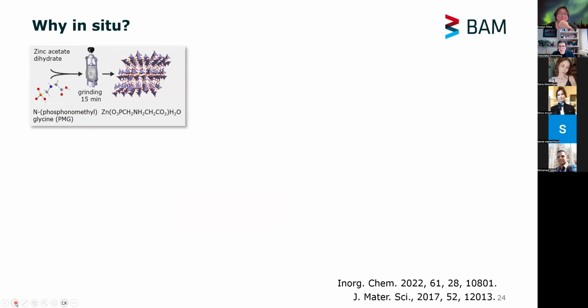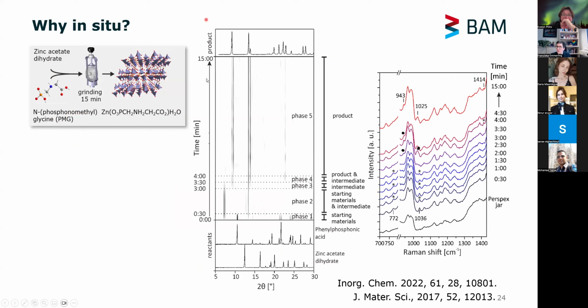I will show that with one example, another MOF we synthesized. And you can see here two sets of data. In the middle, that's the X-ray diffraction. You can see at the bottom and on the top, the educts and the product. And then we look at a top view, and you can see only the traces, similar to a barcode, of what's going on in the reaction. And here on the right side, you can see the Raman spectra. So we can also monitor Raman and X-ray diffraction at the same time and see what's going on.